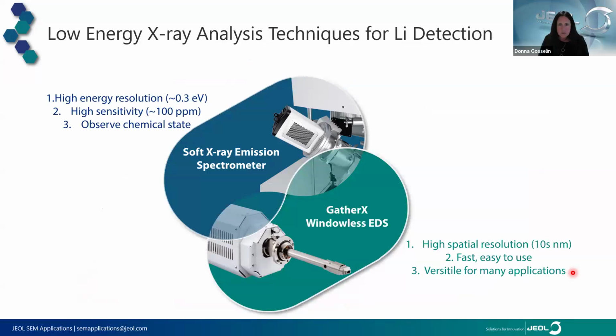I'd like to also introduce, for the next examples, the 2 types of X-ray detectors that are available with our ultra high resolution field emission microscopes or even EPMA instruments that allow for the detection of lithium. The first one is GatherX, which is a windowless EDS detector. It's a spectrometer that is ideal for light element detection. And it's possible to detect down to lithium in the right oxidation state. It's very fast and easy to use as any EDS detector.